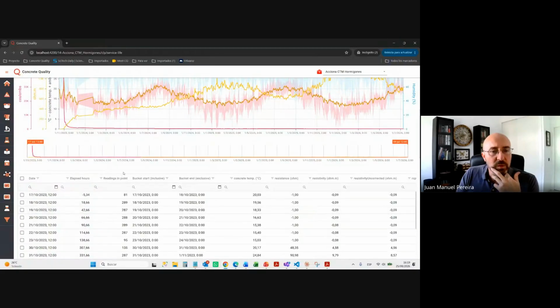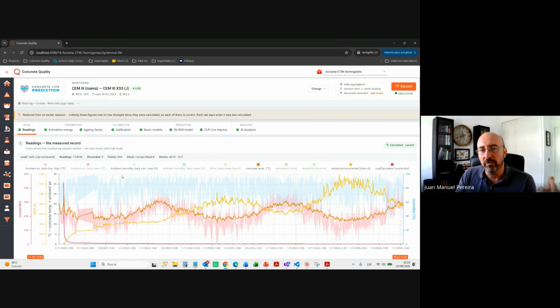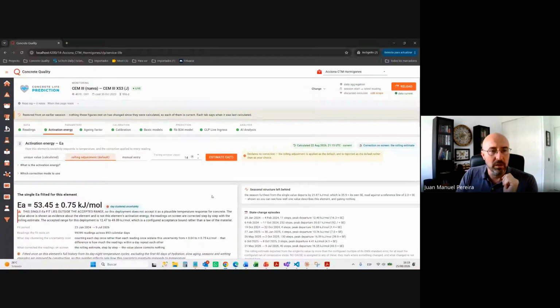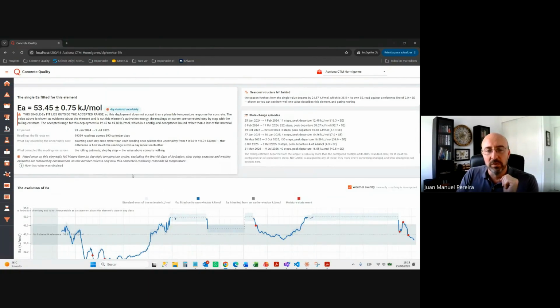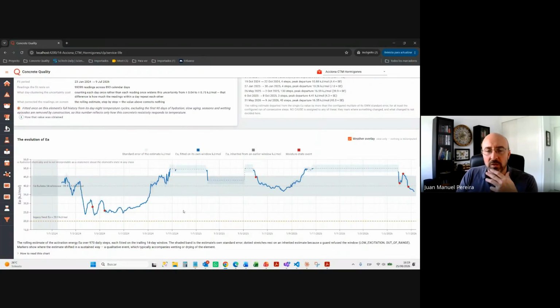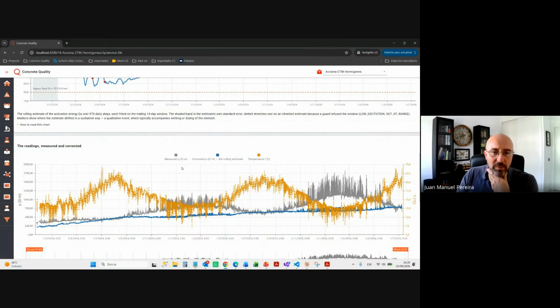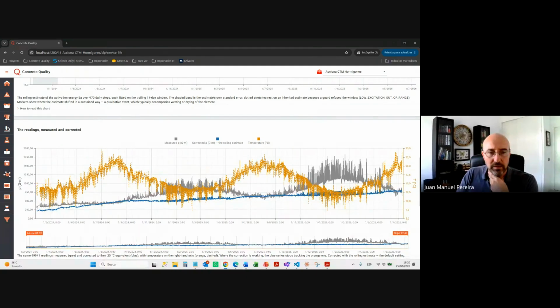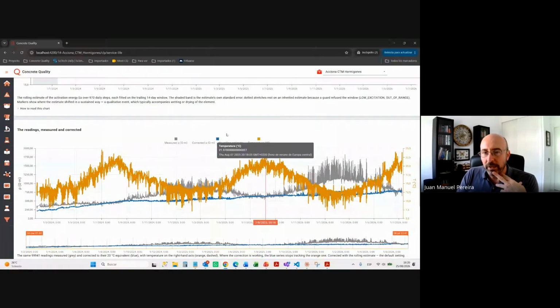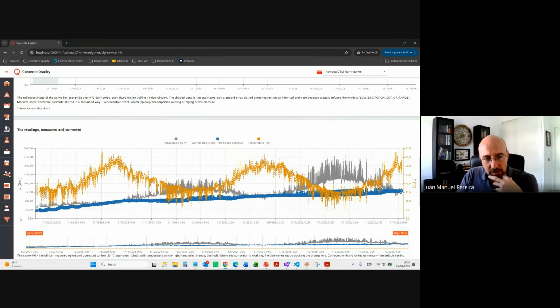Then we do a lot of analysis, and we get a lot of information out of this data. It starts with these two parameters. The activation energy is a parameter that tells you how much the resistivity changes with the temperature change. And there's a lot of complex mathematics to remove the effects of drying and wetting and the moisture, etc. So basically what we get is this yellow, the temperature. You see in gray the readings, uncorrected. And with this correction we get this blue series, which is improving linearly.